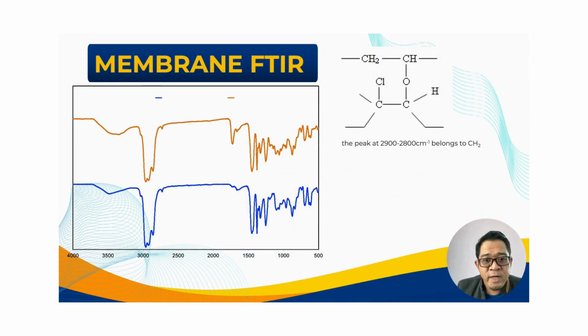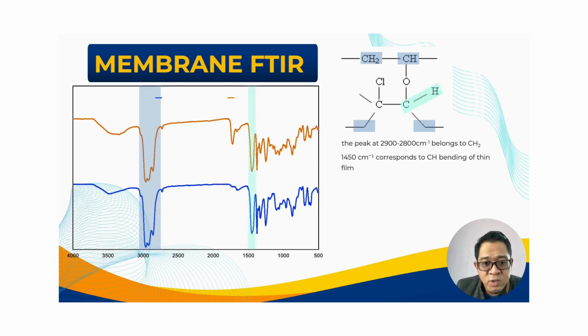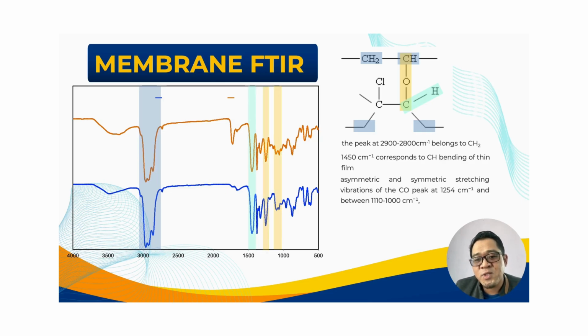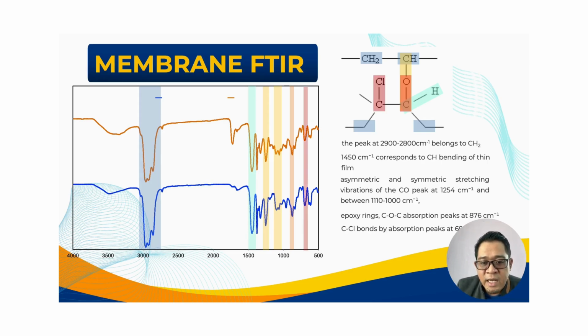We go through the membrane FTIR. So we can see the peak at 2900 to 2800 per centimeter belong to CH2, and then the 1450 per centimeter peak corresponds to the CH bending of the thin film, and then the asymmetric and symmetric stretching vibration of the CO peaks at 1254 per centimeter and between 1110 to 1000 per centimeter. And then the epoxy ring COC peak is an absorption peak at 876 per centimeter. And lastly, the CCl bond shows an absorption peak at 699 per centimeter.